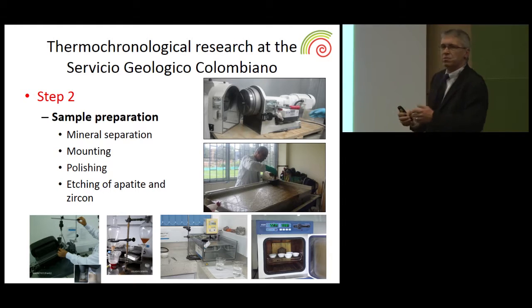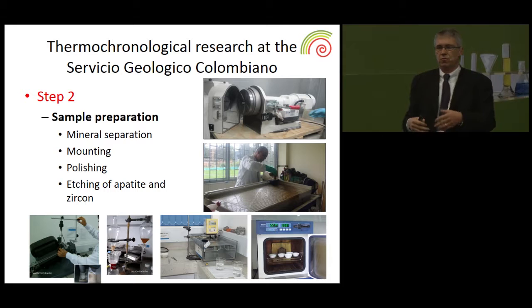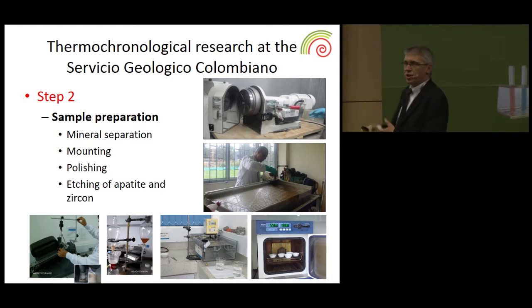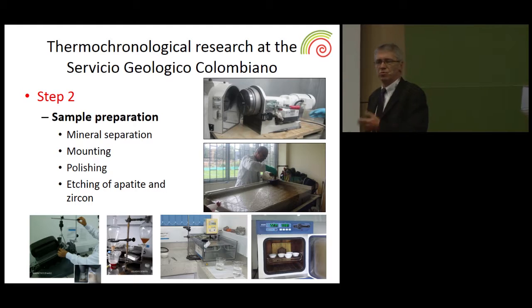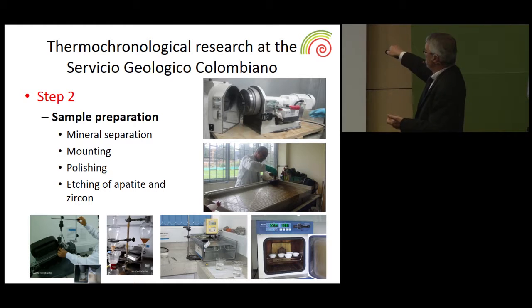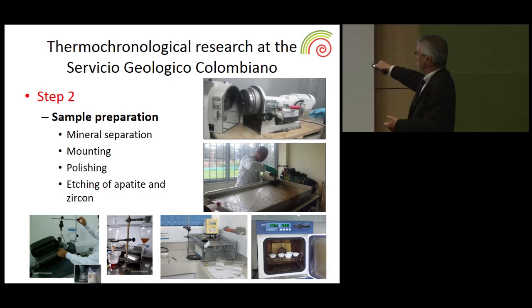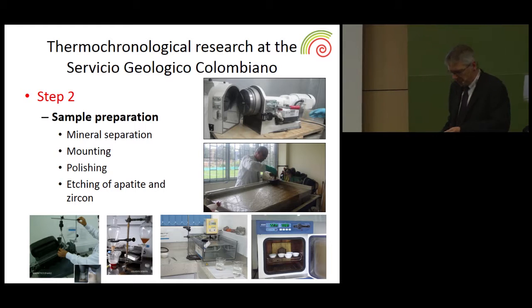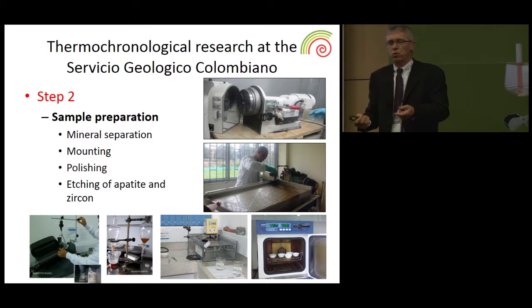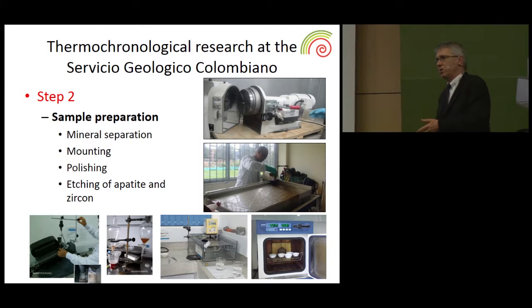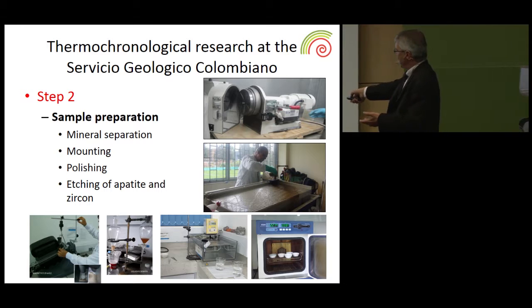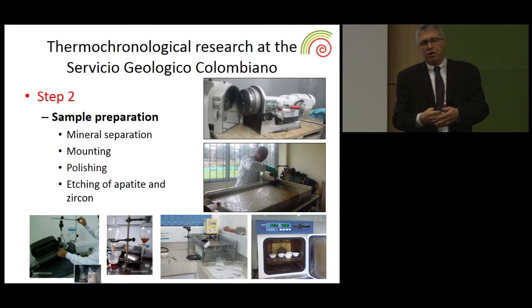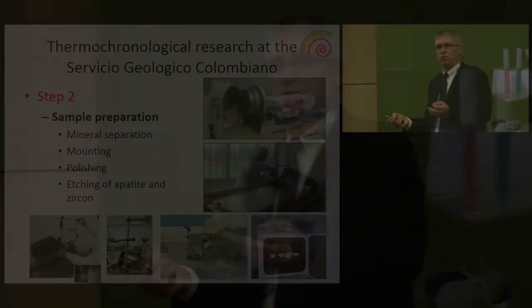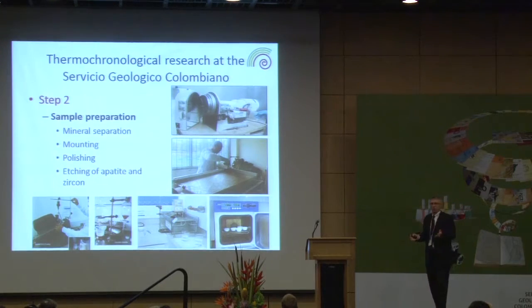After the first step of sampling is, of course, the mineral or sample preparation, which includes, first of all, crushing, sieving, and separating the apatites and zircons, which are heavy minerals. So we use standard mineral separation techniques here in the laboratory of the Geological Survey for hydraulic separation, for magnetic and density separations. So once we have the apatite and zircon aliquots, we can mount them, apatites in epoxy and zircons in Teflon, and we etch them. The apatite etching is very simple: in a 5.5 molar HNO3 solution at 21 degrees Celsius for 20 seconds. This is a standardized technique that basically all the labs around the world use.